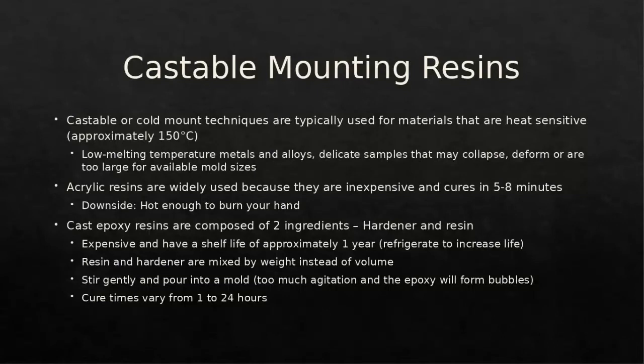Cure times do vary when you're working with epoxy resins. So you're looking anywhere from an hour to 24 hours before you can actually pull the sample out and use it for the metallographic preparation.